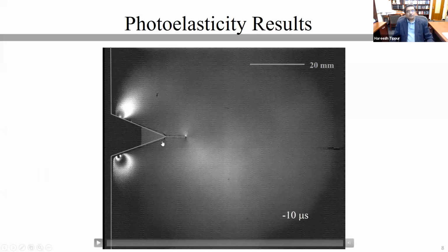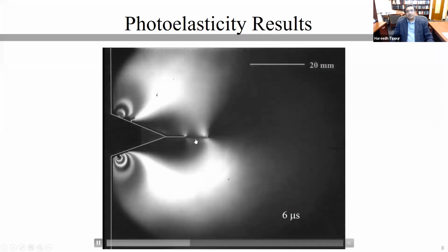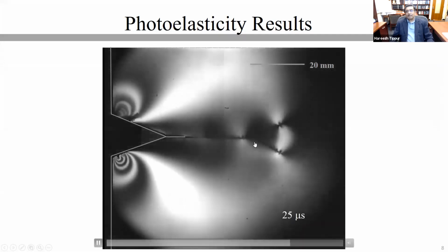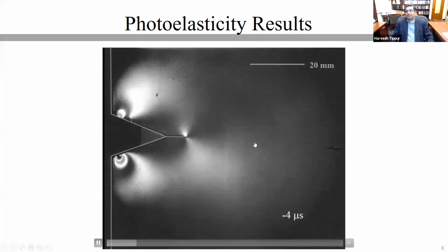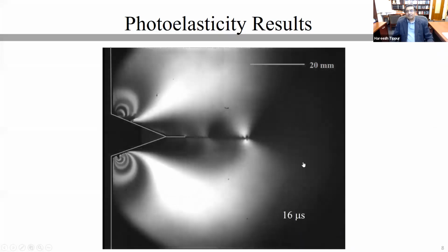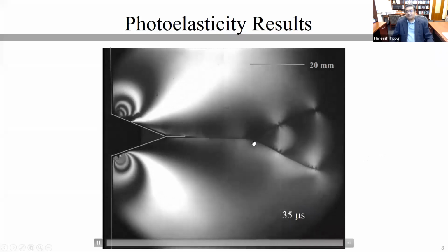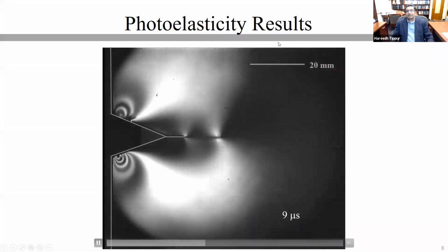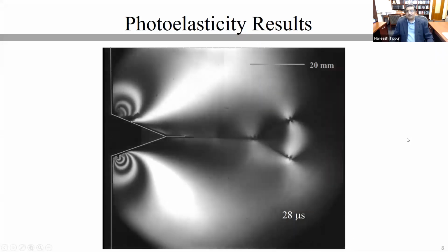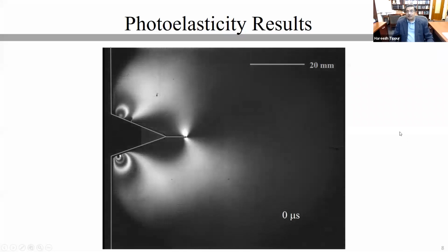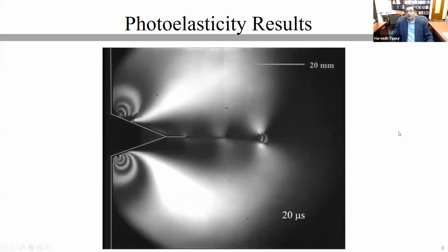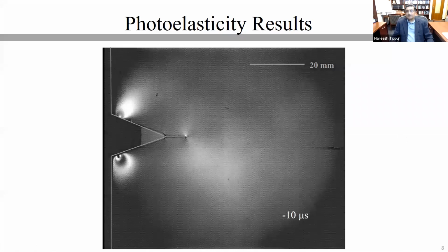end of the long bar, which is tapered and inserted into the notch itself. And you can see the contact stresses that have developed at the time instant 10 microseconds before the crack actually initiated. And when I run this animation, you see that the crack initiates and propagates to the middle of the field of view, and then branches without any provocation. So you can clearly see when it is in the middle, you have these tiny fringes that form at the tip of the, along the crack flanks, and they also travel along the crack faces.